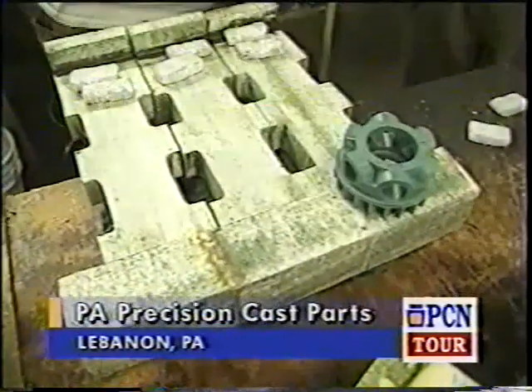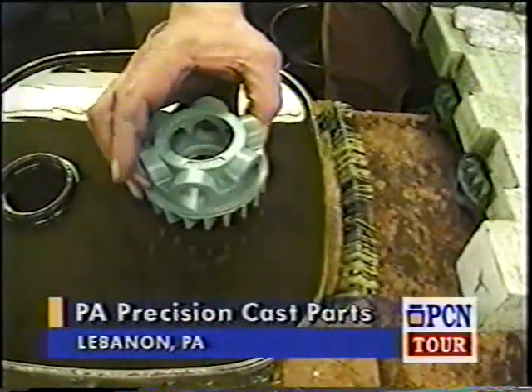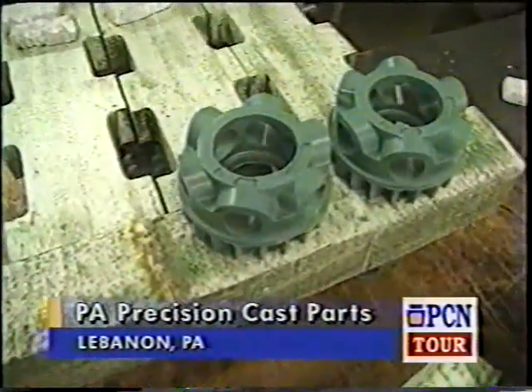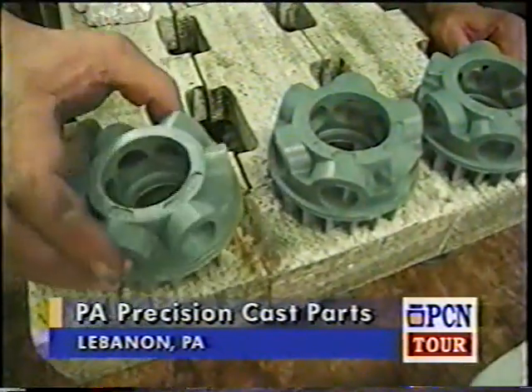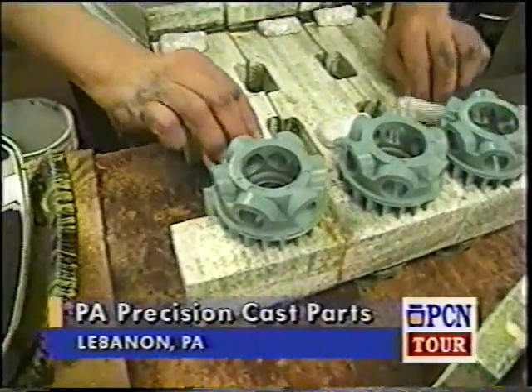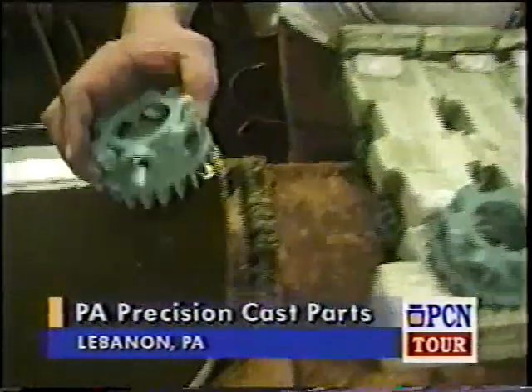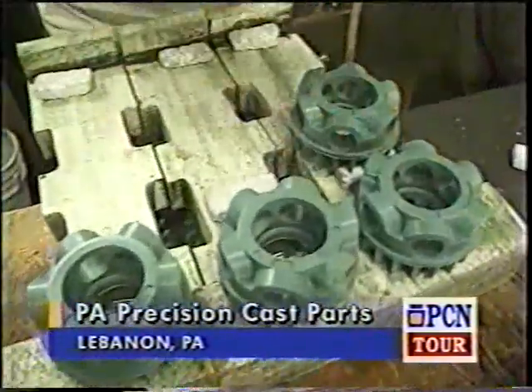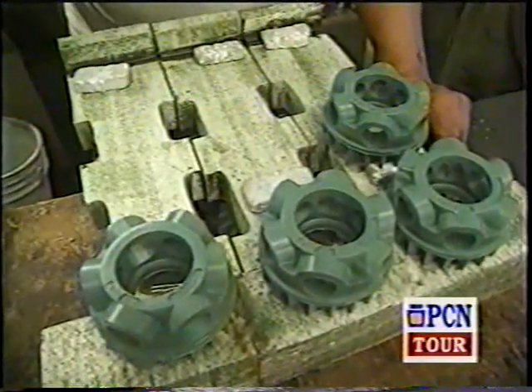Frank is now attaching the wax patterns that he injected prior to the styrofoam. Getting them on accurately is important for the rest of the operation. He's working on 3 separate trees at a time. He'll now put the second row on each tree. The wax that he's using is called a stick-tight. It'll solidify in about 60 seconds.